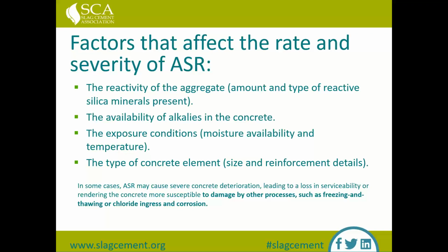ASR damage can work in concert with other types of damage. If you've got ASR damage to concrete, that might promote other types of damage, such as freeze thaw or corrosion, and the vice versa is also true. If you've got freeze thaw damage to concrete, and you've got cracks starting to form, that will accelerate any type of ASR damage.